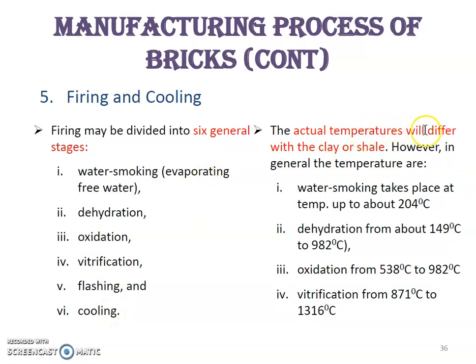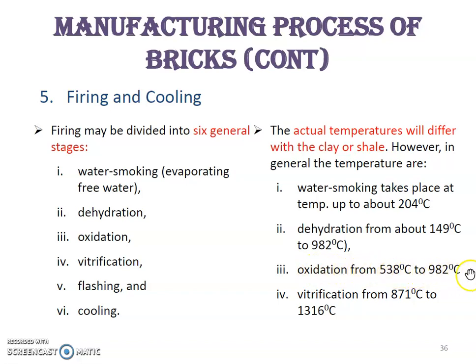The actual temperatures differ with the clay or shale. However, in general, the temperature for water smoking is up to 204°C. For dehydration, it increases to nearly 1000°C. For oxidation, it is from 538°C to 982°C. The vitrification process shows very high temperatures, from 871°C to 1316°C.